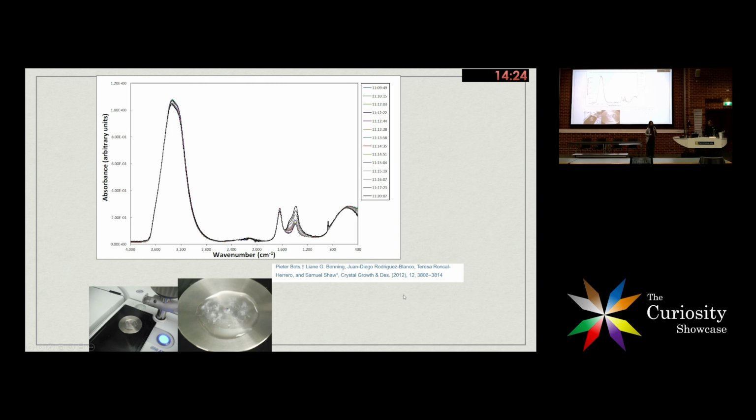And actually finding this paper was a bit of a terrific moment, because in the case of calcium chloride and sodium carbonate, what you find is that at high concentrations, they form a gel. So I was able to use high concentrations of solution, which meant I didn't have a detection limit problem, plus the fact that it formed a gel meant that the diffusion kinetics and everything was slow. So I was able to collect quite a fair bit of timed data to see what was going on during the crystallisation of calcium carbonate.